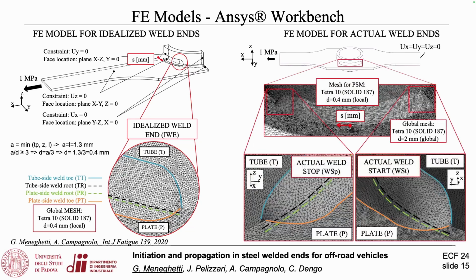The same was done for the real weld ends, and you see here the 4 critical points, as we said before: the weld toe line on the plate side, the weld toe line at the tube side, and the two root lines, plate side and tube side. So all these points along these lines are in competition to initiate the crack.